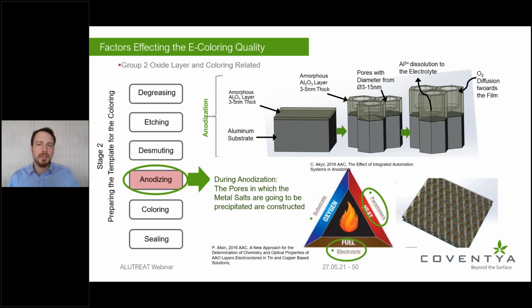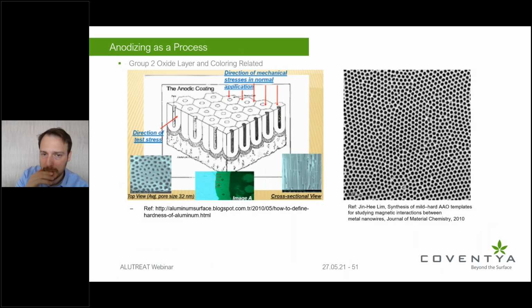So the anodic oxide, and how it is constructed or converted on the surface, will be a key parameter in how our color is distributed and how our color is perceived, because of the way we construct the anodic oxide. As you can see here, this is the thing that everyone wants: a beautiful honeycomb-like layer structure, distributed evenly. That means we have a very good distribution of our pores and metal salts, but also a very transparent layer with minimum integral coloring, which means minimum discoloration of the layer.